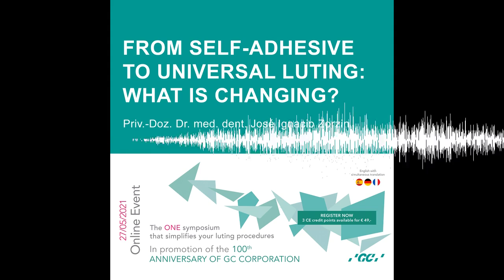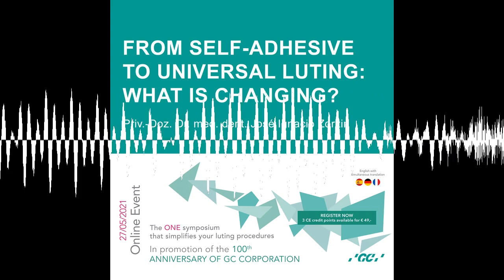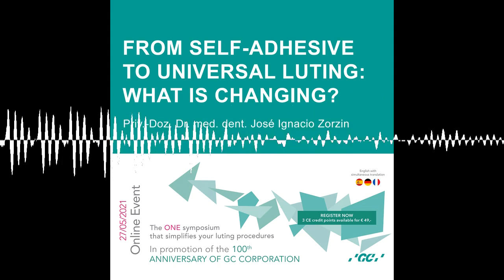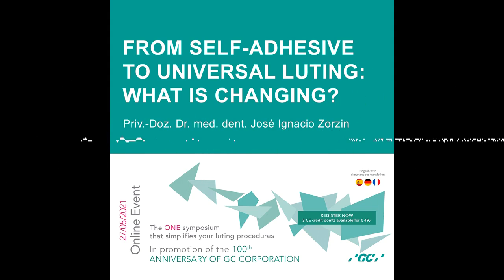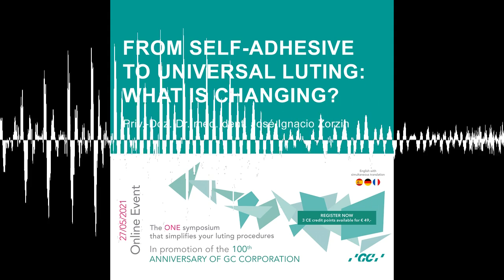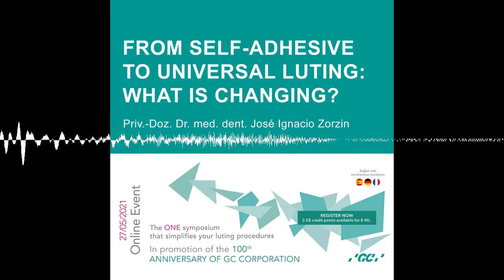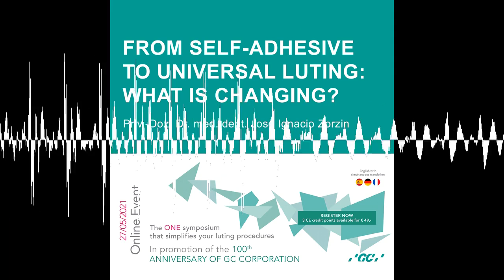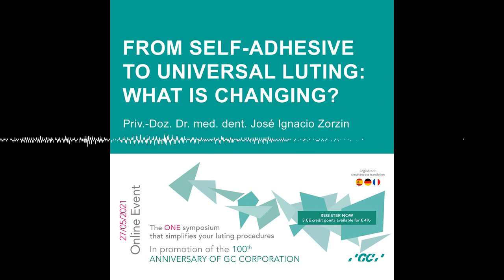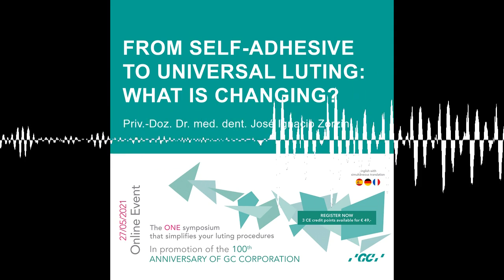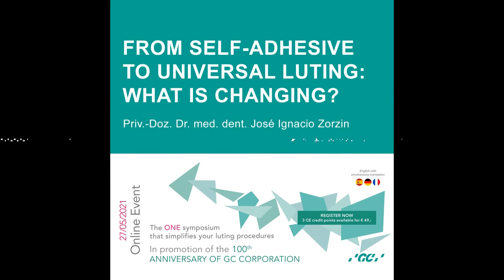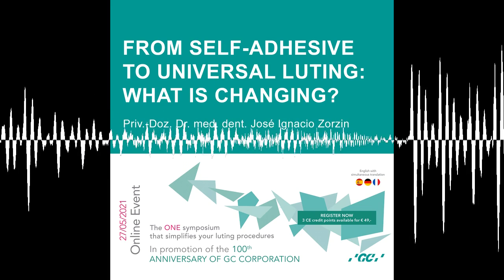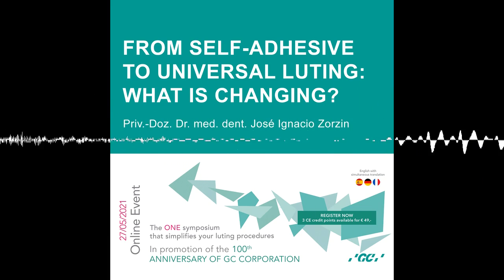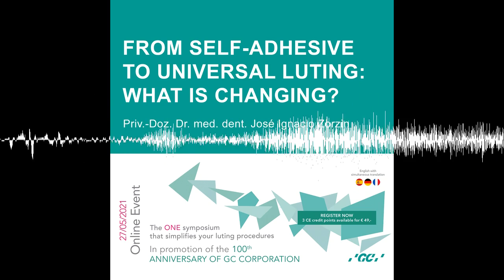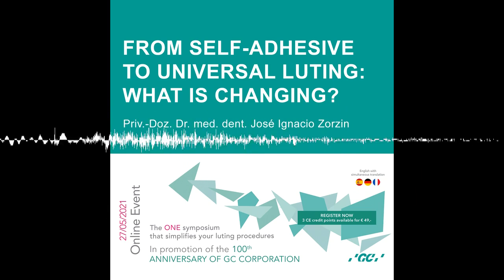We have to see. So the zirconia Maryland bridges are typically dual cure or self-cure? Well, Maryland, it depends a little bit. For example, if you get restorations which are luted mainly to enamel, then you have to go maybe for a classical pathway of adhesion with etching the enamel. But if you've got a lot of dentin surfaces, then self-adhesives will work fine. I think we basically covered it.